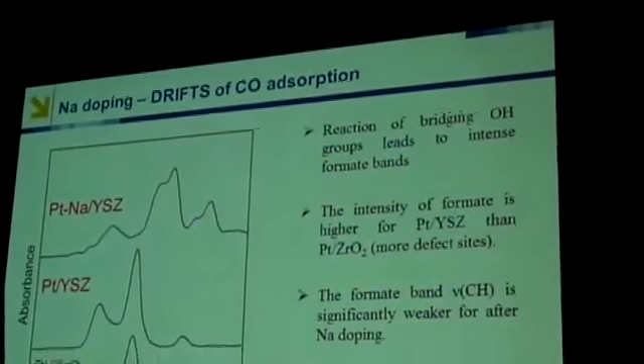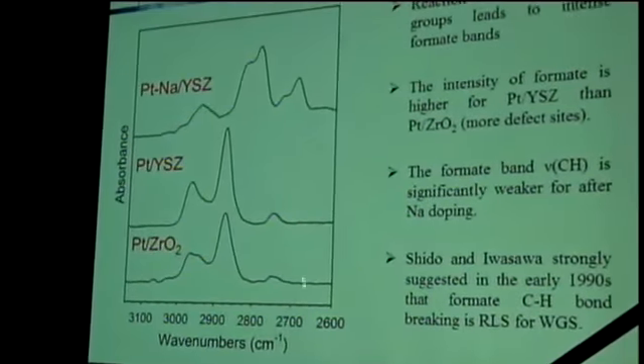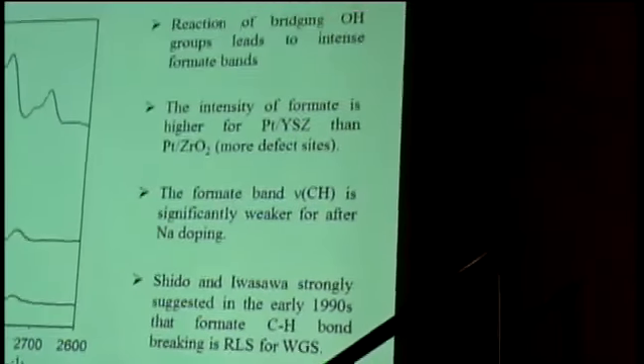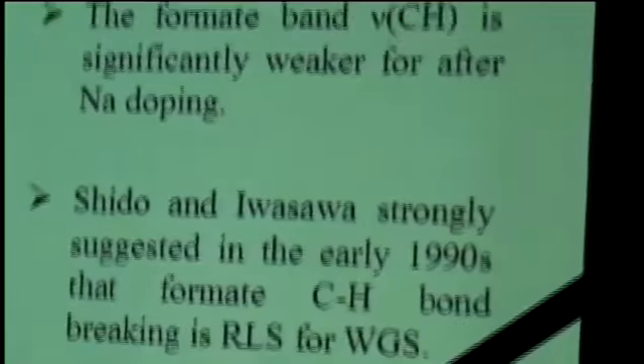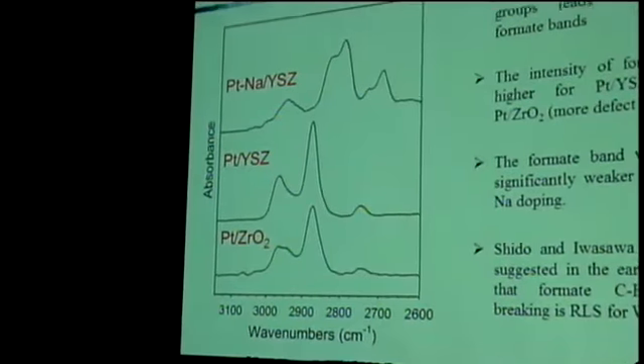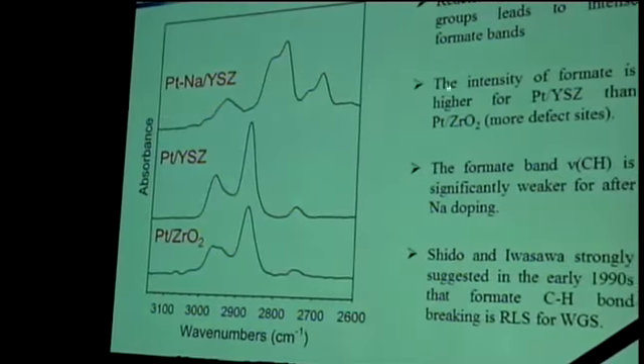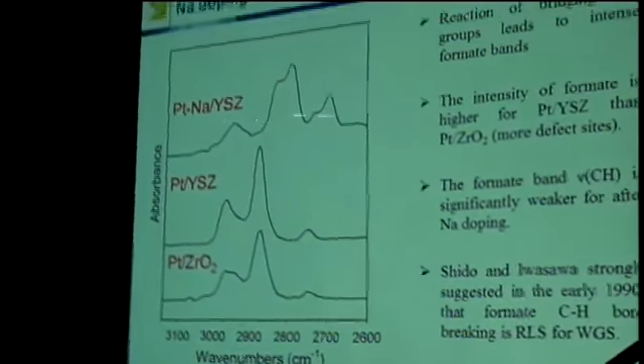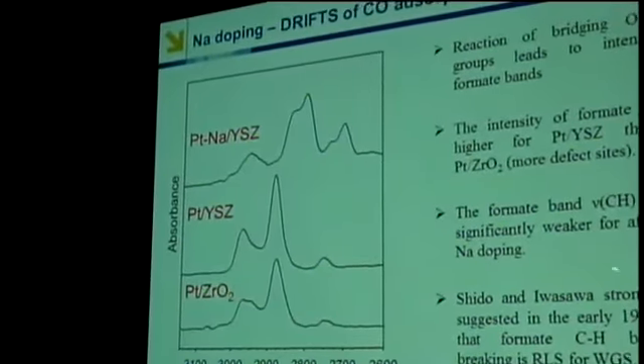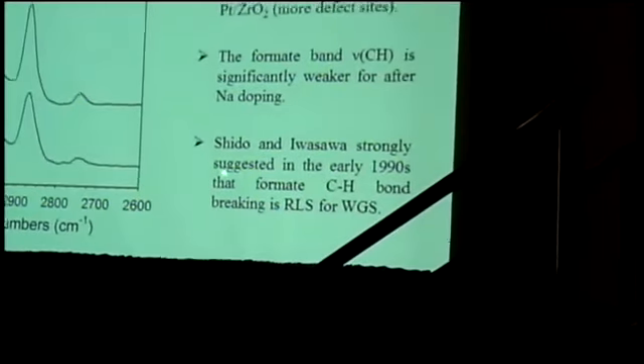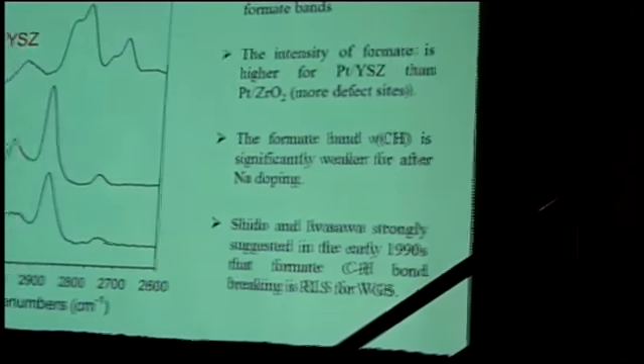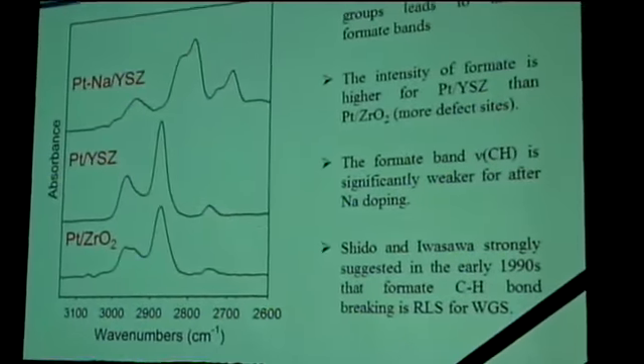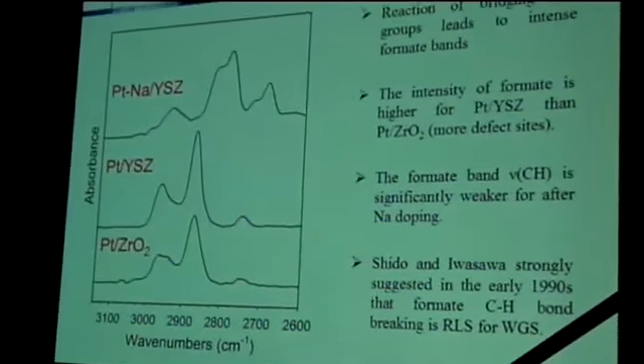So what is going on with sodium? Well, as I mentioned before, when we probe the defect-associated OH groups with CO to form formate, we had a higher intensity when we added yttrium, indicating increased number of defect-associated OH groups. When we add sodium, there's an electronic modification of the formate, where there's a weakening of the CH bond of the formate. Now, back in the early 90s, based on some kinetic isotope effect studies, Shido and Iwasawa strongly suggested that formate-CH bond breaking was the rate limiting step for water gas shift. And of course, that's been highly debated, but this weakening is certainly consistent with that viewpoint.